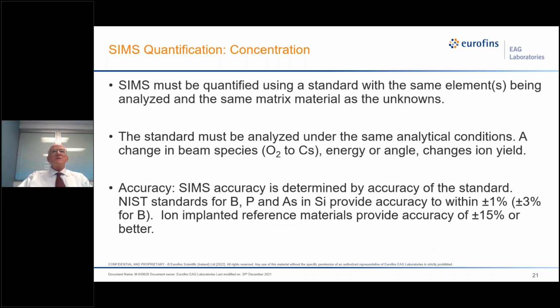SIMS must be quantified using a standard of the same elements being analyzed in the same matrix as the unknowns. The standard must be analyzed under the same analytical conditions, and generally we analyze, well, always we analyze the standards right alongside the analytical samples. The accuracy of SIMS is determined by the accuracy of the standard.